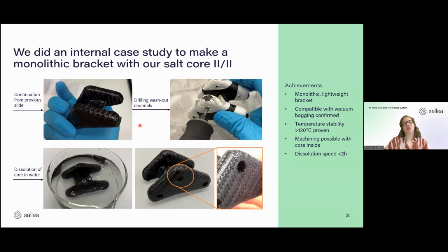And what we did is actually we were drilling the washout channels into the core. Now we did it all manual, so our engineers did this all manual. So you can see we just put some reinforcement around where we drill in, to make sure that we do not have too many fibers breaking out. And then basically we created 3 holes, one here, here, and here on the lower end, and then let it sit in the water.